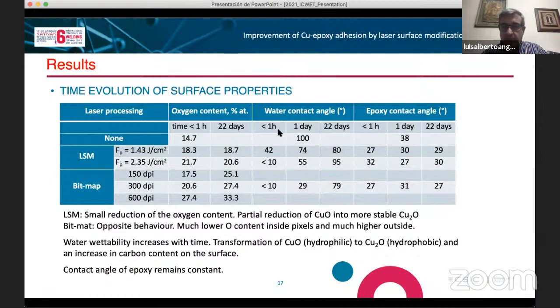This is reflected in the water contact angle. So if you look at the hydrophobicity, you see that the contact angle increases with time, reaching values close to 100 degrees in the case of the laser line scanning mode. But we have also checked the evolution of the epoxy contact angle, and in that case, you will see that the evolution is very similar, and it doesn't depend on time.